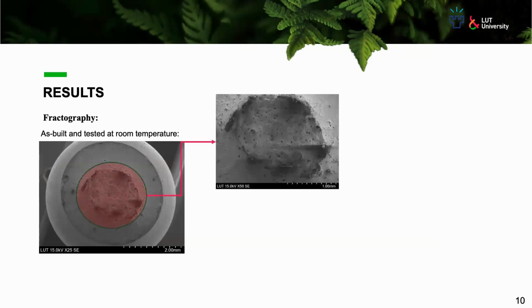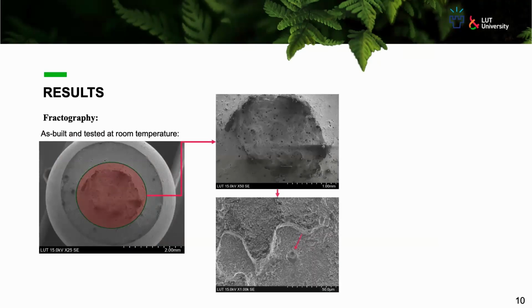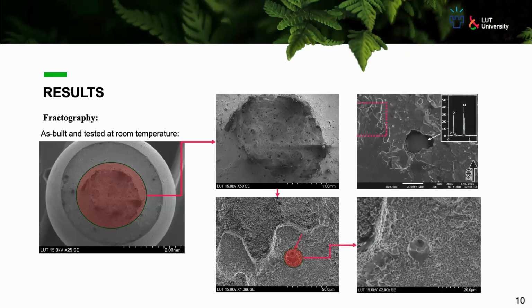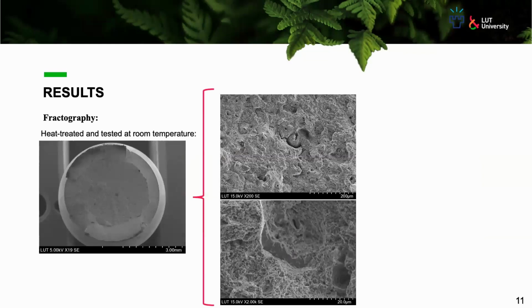And in the case of as-built samples, the damage was fully ductile. As you can see here, even close to the shear lips, the signs of ductile failure are apparent, except for these huge voids that we believe were initiated by these detected aluminum oxide particles that were randomly distributed in the microstructure. However, in the heat-treated version, the fracture was quasi-cleavage or semi-ductile.